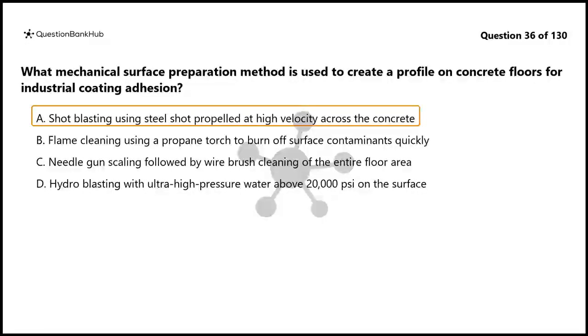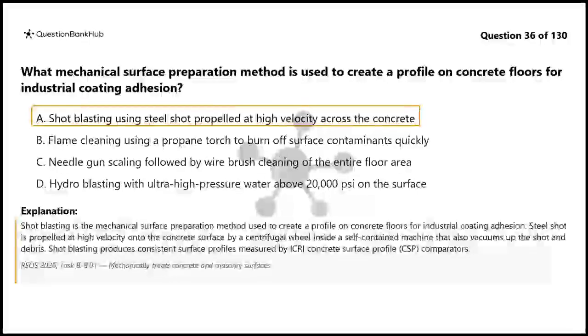The correct answer is A. Shot blasting is the mechanical surface preparation method used to create a profile on concrete floors for industrial coating adhesion. Steel shot is propelled at high velocity onto the concrete surface by a centrifugal wheel inside a self-contained machine that also vacuums up the shot and debris. Shot blasting produces consistent surface profiles measured by ICRI concrete surface profile, CSP, comparators.